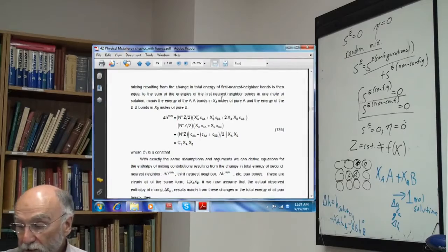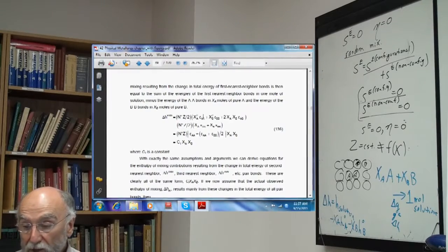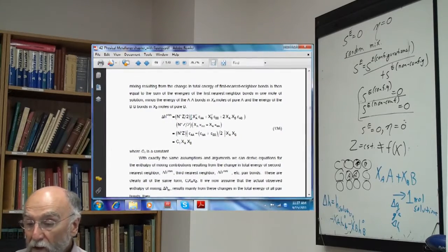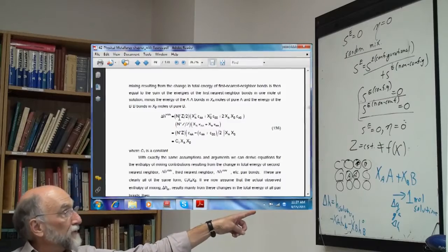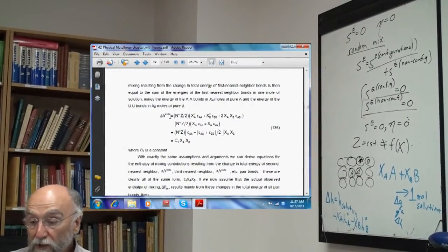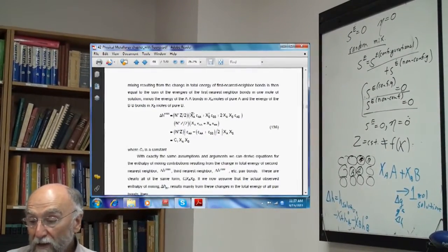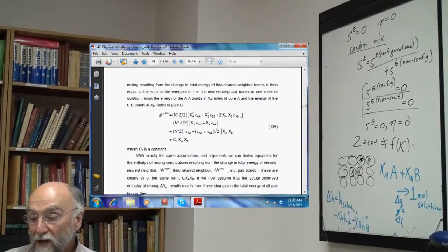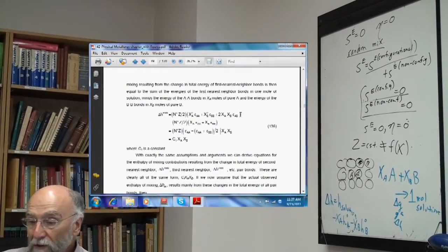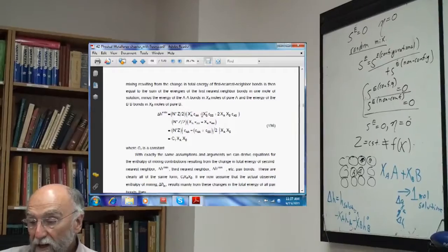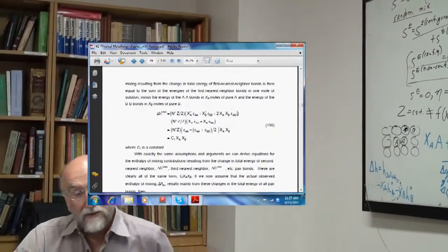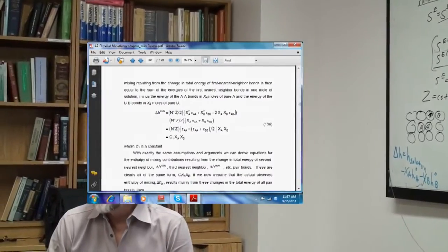Okay, so it's equal to the total number of bonds, which is N naught Z over 2. Now I'm trying to get this H, the enthalpy of the solution. This first term is going to be the enthalpy of the first nearest neighbors in the solution. Now these epsilons, AA, BB, and AB, are the bond energies. And again, we're assuming that the epsilons are independent of composition and temperature, just like the Z.